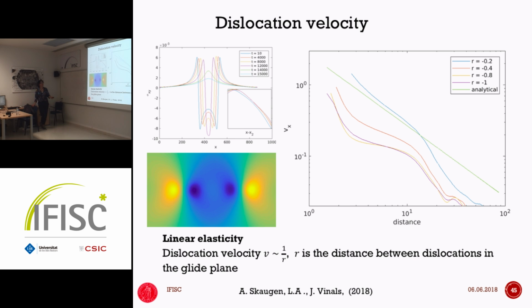In particular, we see a huge difference when we look at the velocity of a dislocation. In this case, the dynamics of the dislocation is driven by the local stress, and the stress is induced by the other dislocation. So there is a stress acting on the second dislocation, right? So they move with respect to the internal stress generated by each other. For the velocity of one dislocation, in this case the motion is only glide, so we only have the Vx component. If you track Vx as a function of the distance, we see that for different quenching depths, the green line shows you the 1 over r prediction from the linear elasticity, that the velocity is going to go as 1 over r.